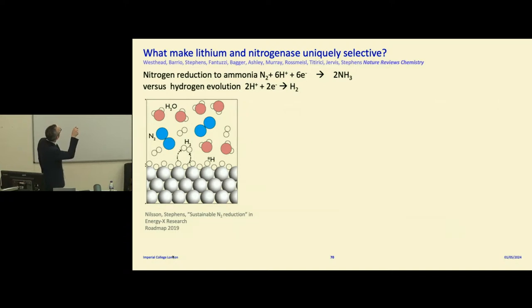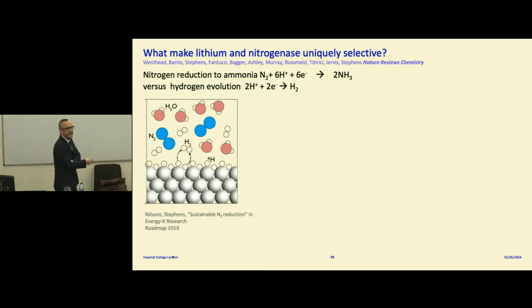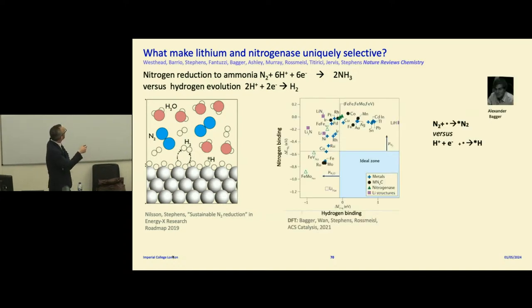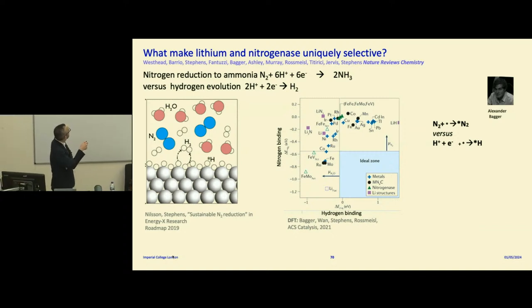hydrogen evolution. Nitrogen, these blue atoms here, is very inert, and hydrogen is a lot more reactive. And typically, hydrogen will bind to the surface and stop nitrogen from getting there. So I asked my theorist collaborator, is there something special about nitrogenase and lithium that allows it to work? And the answer is simply no. Even nitrogenase and lithium bind nitrogen strongly, but they bind hydrogen a lot stronger. So if you put lithium or nitrogenase into an aqueous solution, you always get this picture: the surface poisoned by hydrogen.